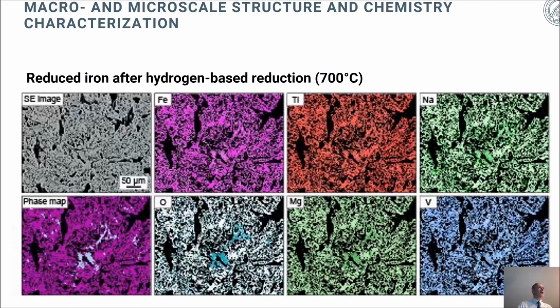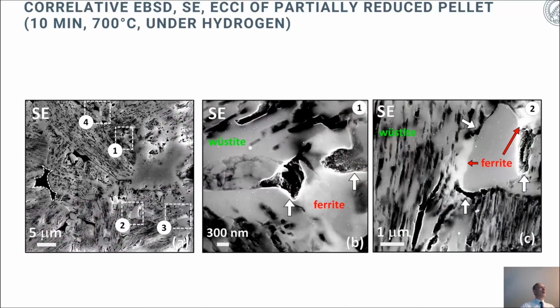Here you see again a pellet that has been reduced by pure hydrogen at 700 degrees centigrade. So all the data are taken at 700 degrees centigrade. And then you see how some of these chemical features, of course, prevail over the reduction. And we will later look at this, as I said, in more detail. The message of this picture is just to remind us that we inherit complex structural features and complex chemical features when we deal with the understanding of the role of microstructure and internal fracture and internal kinetics on the overall hydrogen-based reduction.